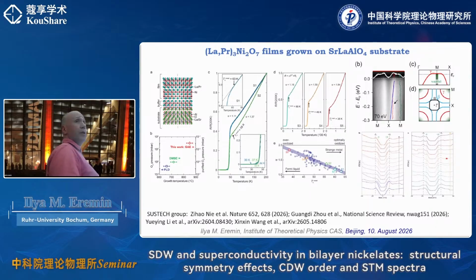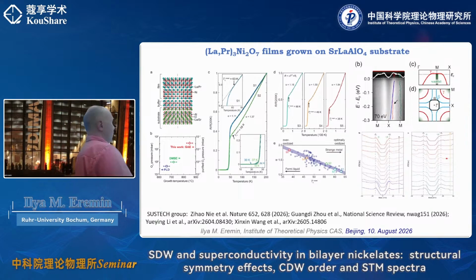Furthermore, there have already been ARPES measurements and STM measurements. I will be talking about the first STM measurements later today, made by the group of Haihu Wen from Nanjing. But all the information about fermiology, which is needed to understand superconductivity, comes from thin films. Importantly, they see these bands that I will be discussing later theoretically, the alpha, beta, and gamma Fermi surface sheets, and the gamma pocket is indeed crossing the Fermi level and forms a kind of waterfall structure, which is very interesting.